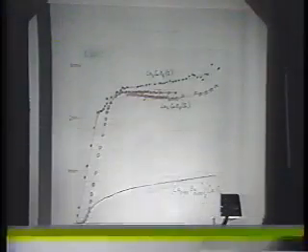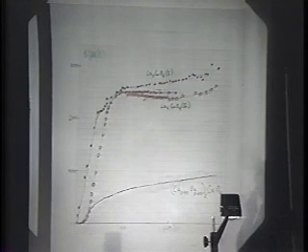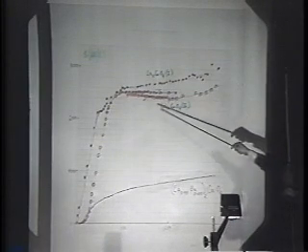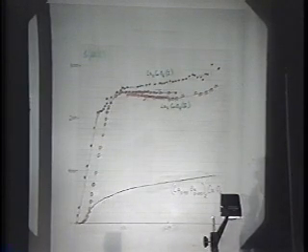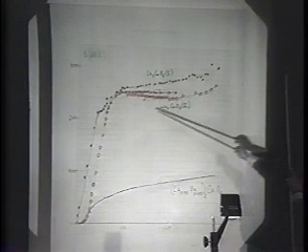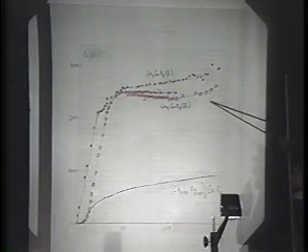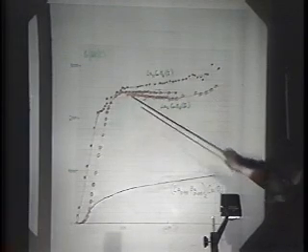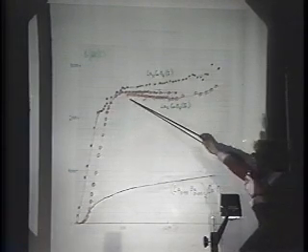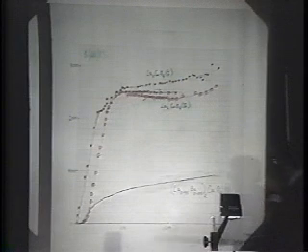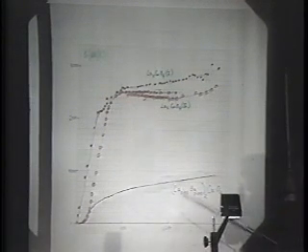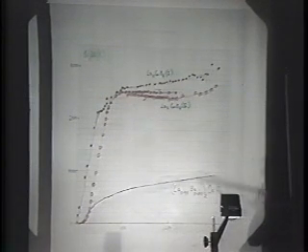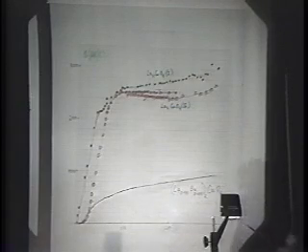So this shows some experimental results on what we call the pure stuff. This is 2 independent preparations of lanthanum copper oxide. And you can see that the main thing is a temperature-independent large positive thermopower, indications of superconductivity, perhaps from the surface at high temperatures, 80 K, then falling nearly to 0. And then with very small amounts of barium, the thermopower really shoots down.